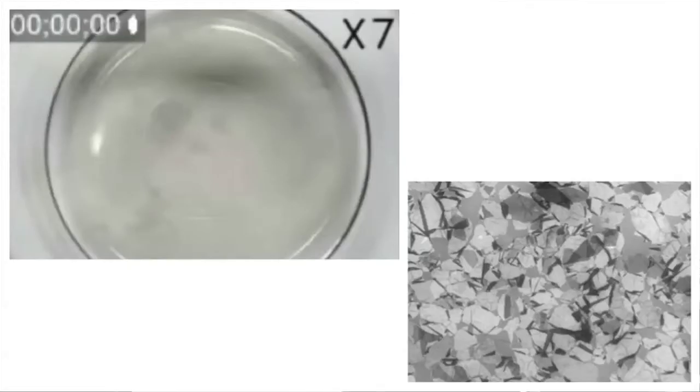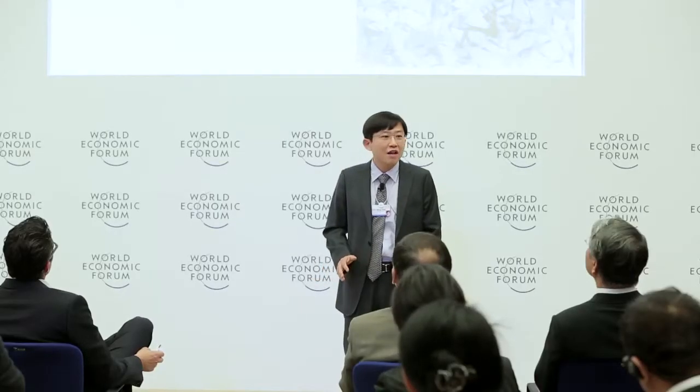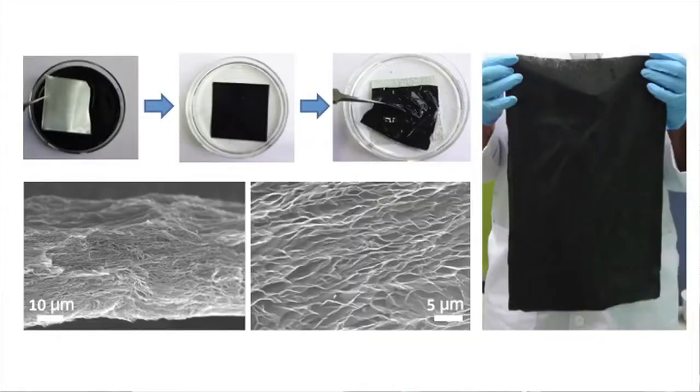This video shows that very fine nanoscale graphene particles can be assembled into a large area film in a very fast way. We can get a 10cm diameter highly uniform graphene film by a 2-minute assembly at a water surface. We also demonstrated that graphene flakes can be assembled into large area porous film structures at a metal surface by layer-by-layer self-assembly. This is a really scalable process, so we can get very large area graphene gel films based on self-assembly.